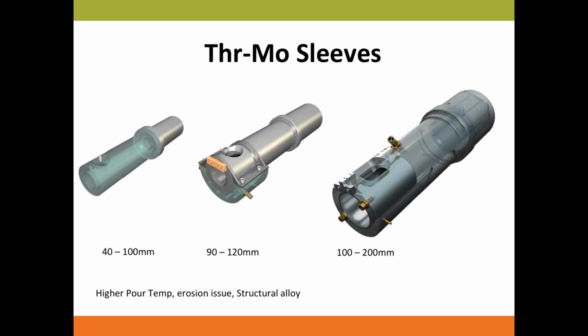So you have a choice, when you are die casting aluminum with a very high pour temperature, let's say maybe 700 or 710 degrees Celsius because of your process requirements, or you're die casting some structural alloys, or you do see some erosion issue, especially under your pour hole area, we would suggest you use Thr-Mo sleeves. On different sizes, we will have a different design for the sleeves as well. And on the larger ones, you can have an insert only, because the insert is the area that sees the most temperature fluctuation and most erosion as well.